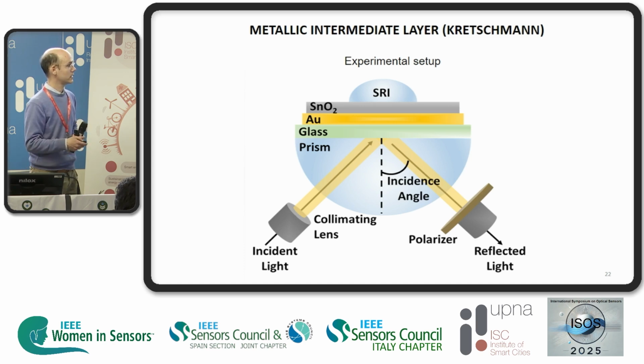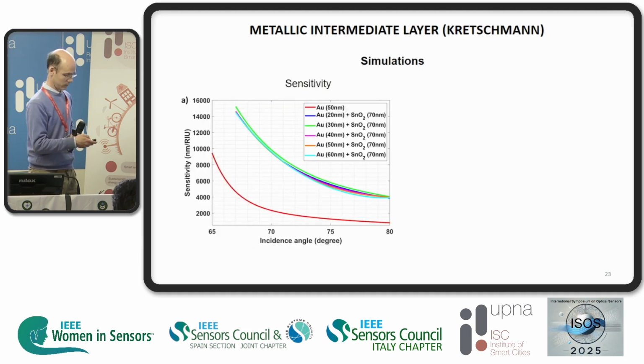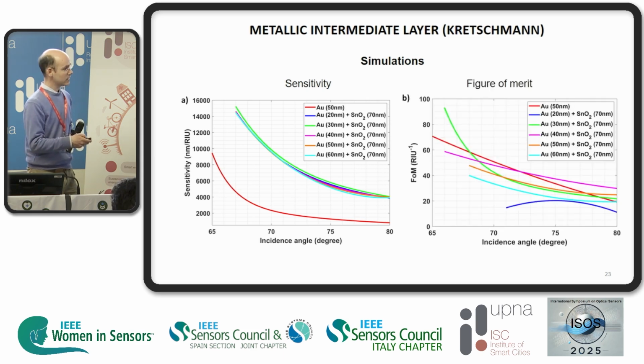Going back to the idea of the incidence angle, we decided to explore the metallic intermediate layer in Kretschmann configuration. This is the setup we use with the optical prism, the gold layer, the tin dioxide layer. And with simulations, we can observe that the sensitivity increases a lot as a function of the angle as we approach the critical angle, both for just the gold layer structure and for gold plus tin dioxide. Regarding the figure of merit, things are not so clear, but what is clear is that going to lower angle of incidence increases the figure of merit.